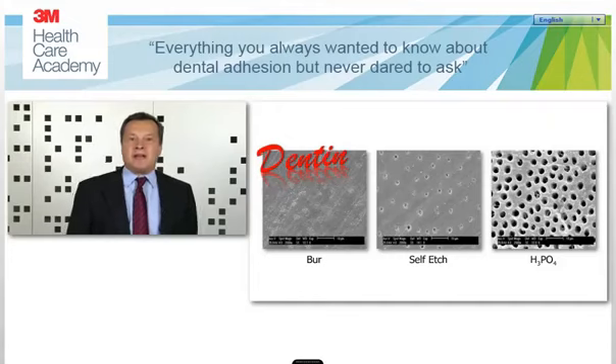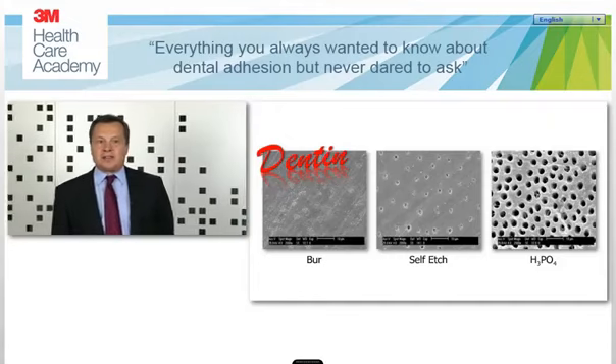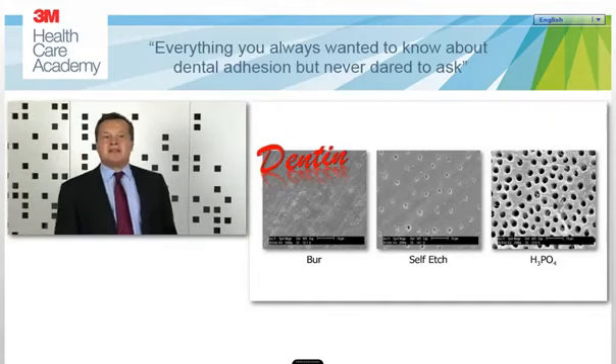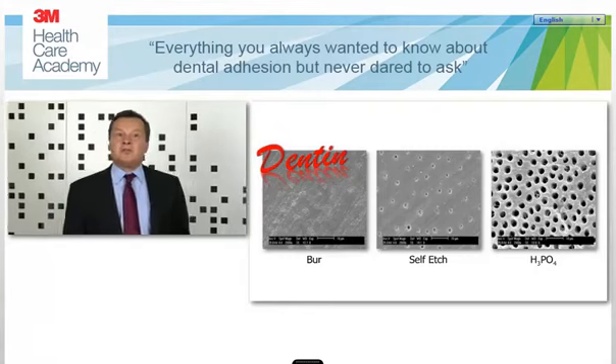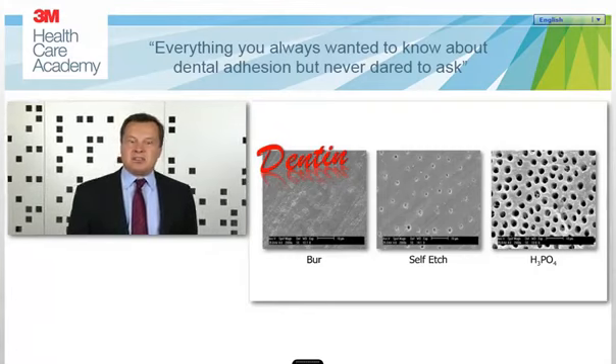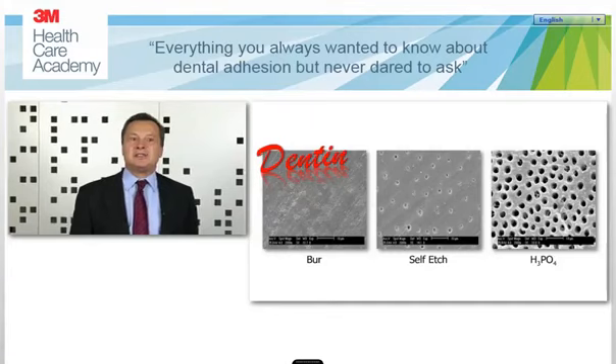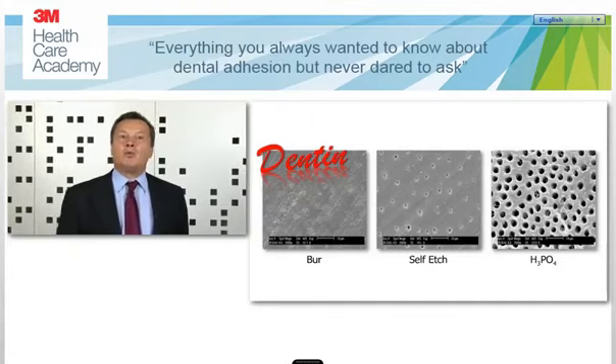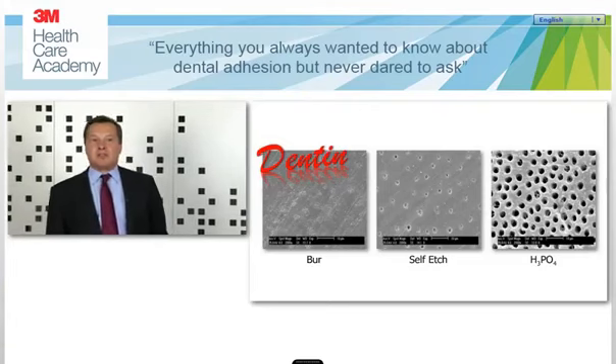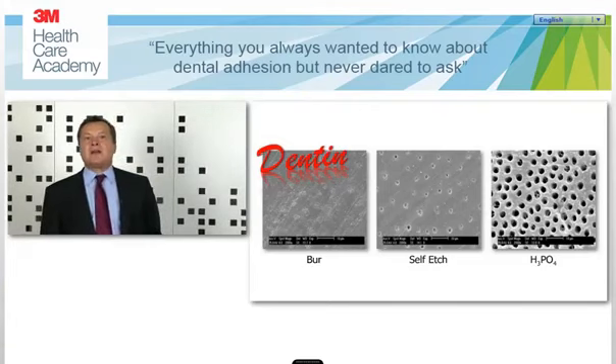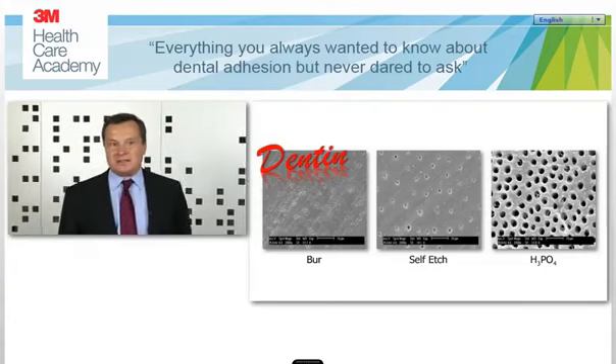And when you apply an aggressive acid, for example, phosphoric acid on dentin, you can see that the smear layer is completely removed, but also the substrate, which is dentin, is attacked. And this is the reason why these dental tubuli are really wide open, and why also the superficial portion of dentin is quite aggressively demineralized.